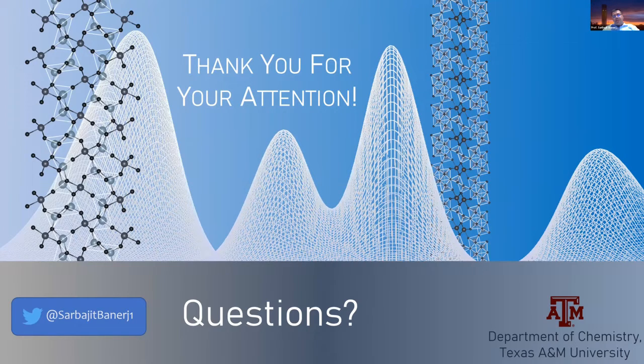Yeah, that's a really good question. Thank you. It's a really emerging technique, and it essentially does imaging using coherent diffraction patterns. It has to be performed at a synchrotron. It's fairly specialized, but instead of doing absorption spectroscopy like we do in STXM or in scanning transmission X-ray microscopy, in ptychography we use coherent diffraction imaging. So you actually use the diffraction pattern.